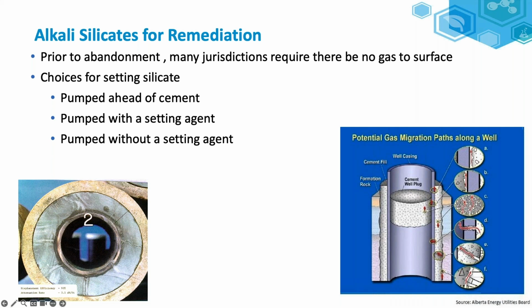The other option is to pump the silicate with a setting agent. So in the case of making a silicate gel, an acid generating material would be mixed in with the silicate. Set times could range from instantaneous to several hours, if not a day. And the other option, you know, questions about CO2, H2S, that would be the other way to set it up. So if there was CO2 coming into the well, pumping the silicate in, eventually the CO2 would overcome the buffering capacity of the silicate and you'd form a silicate gel. So you would not need a setting agent in that case. Likewise, if the water was high in calcium, you'd pump it into that and it would form a calcium silicate upon contact.